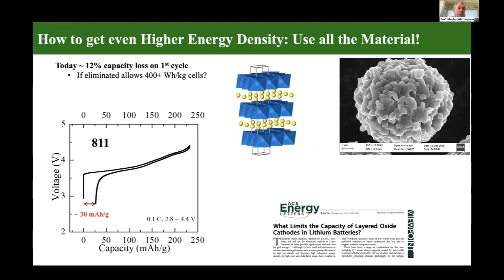So let's look at how we get higher energy density, higher capacity out of these materials. It turns out all these layered materials show what we describe as a first cycle capacity loss. And this shows you a typical cycling curve here. We charge it up to about 4.4 volts, we discharge it, and then we're losing, in this case, about 30 milliampere hours per gram. This is typically 10 to 15% loss, and you do not get that back in subsequent cycles. So the issue is, can we reduce that loss? Because this is very important, because this is at a low potential, about 3.5 volts, where the electrolyte and the cathode are the most stable. To get higher energy densities, we'd have to push the voltage higher, and we know the electrolyte is not stable. So we need to work out why that happens and how we can solve it.